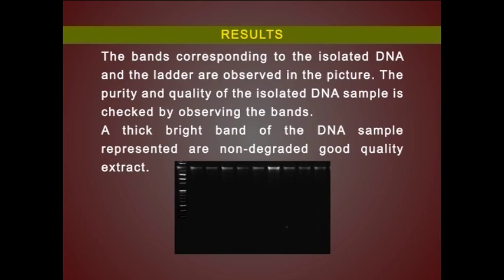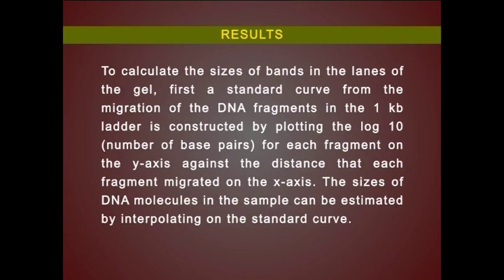A thick, bright band of the DNA sample represents non-degraded, good quality DNA. To calculate the sizes of bands in the lanes of the gel, first a standard curve from the migration of the DNA fragments in the 1 kb ladder is constructed by plotting the log 10 of the number of base pairs for each fragment on the y-axis against the distance that each fragment migrated on the x-axis.